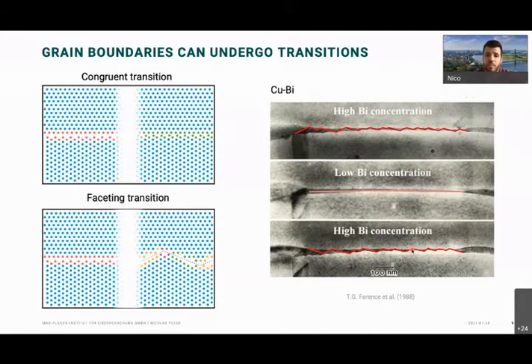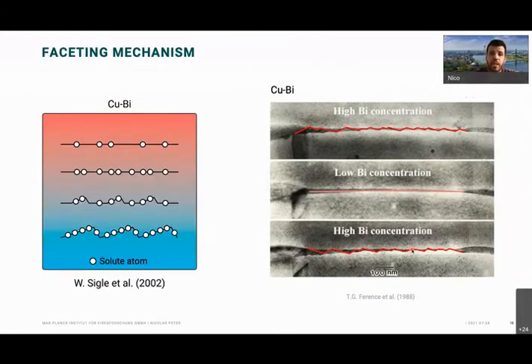There's a lot of work about temperature-induced faceting, but not so much about chemically induced faceting. For this exact case, Sigle came up in 2002 with a mechanism which says that at high temperatures there is some bismuth at the boundary. If you cool it down, more bismuth goes to the boundary, eventually exceeding a certain threshold to form a facet, a little facet which is decorated in bismuth. Then more bismuth decorates the entire boundary, so the whole boundary is decorated in bismuth.